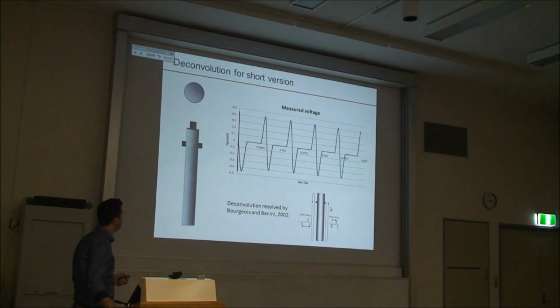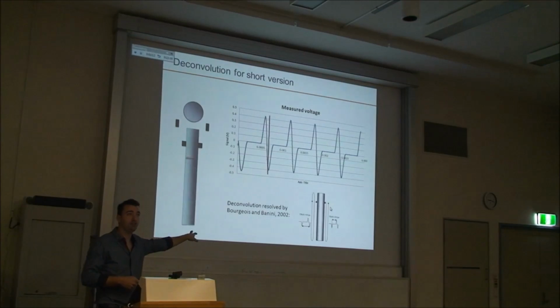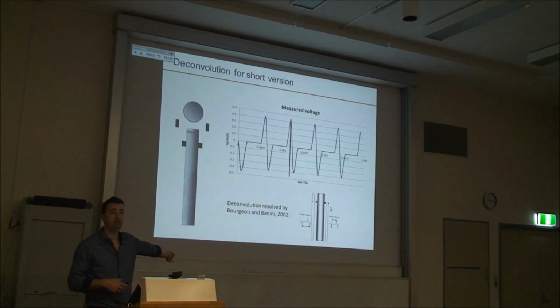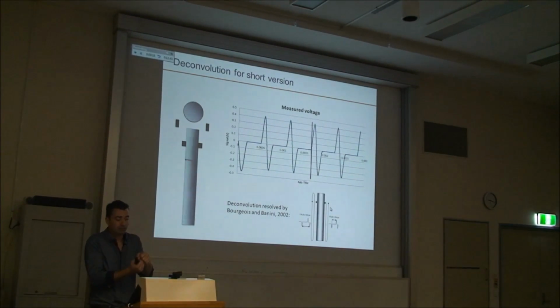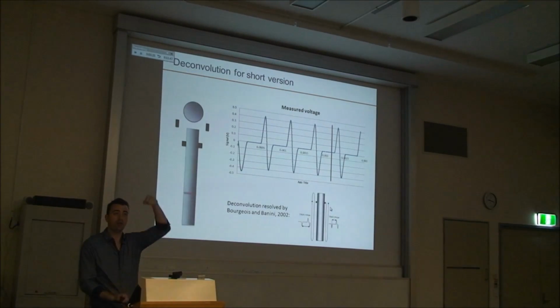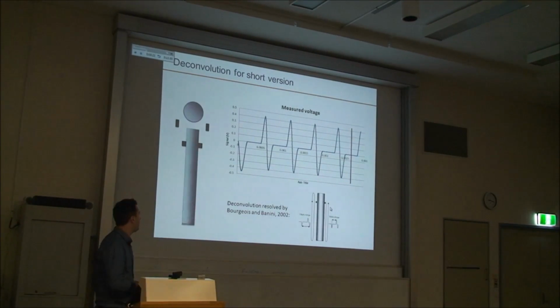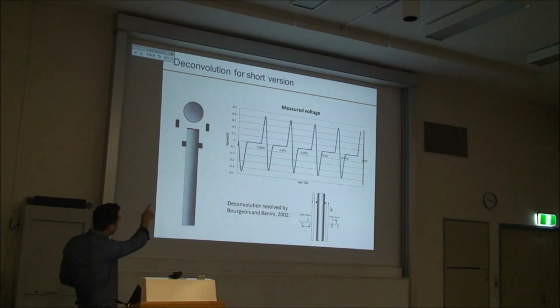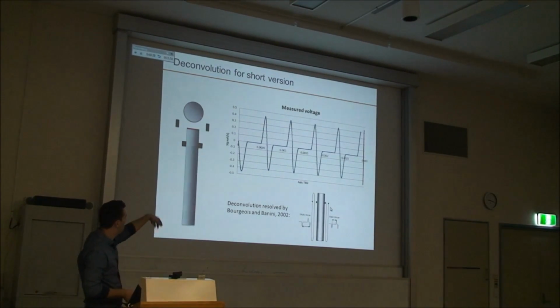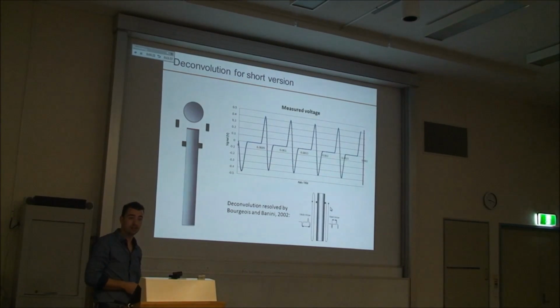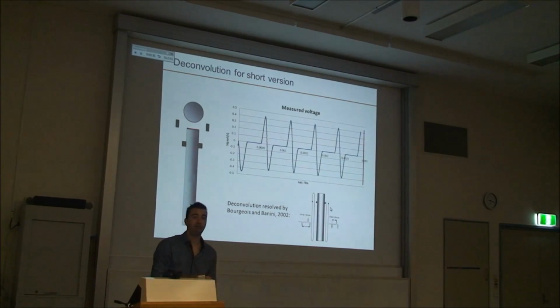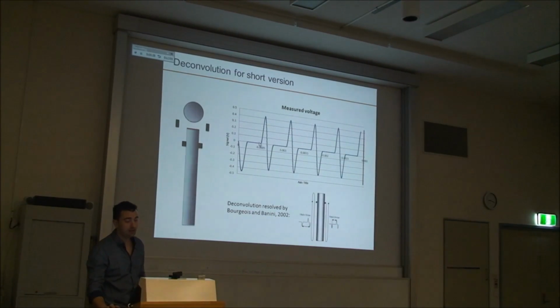The trick about this device and what was designed here in 2002 is the deconvolution analysis. This shows that when the compression wave hits the bottom of the bar, it's going to be reflected and transformed into a tensile wave. So the bar is going to vibrate like that, very quickly. It can travel up and down in less than microseconds. But by knowing the length of the bar and the properties of the rod, you can predict when this signal is going to come back. And by doing that, you can do deconvolution of the signal.